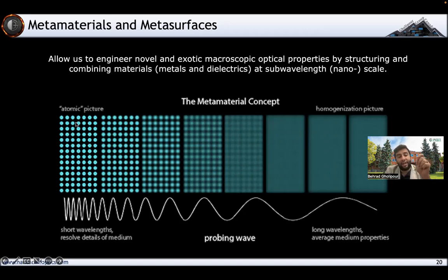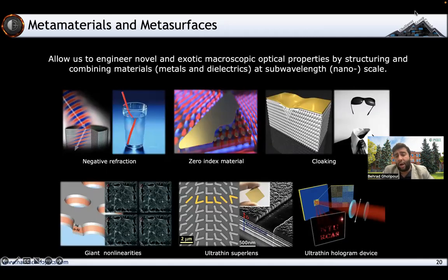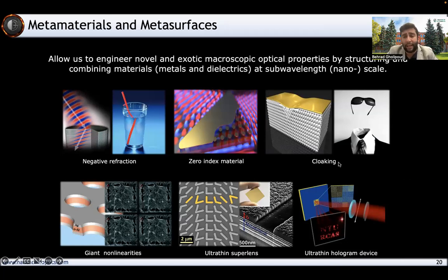But we've very carefully engineered each metamolecule, each of these little nanostructures, nanoresonators, so collectively they all couple together and have a response that the wavelength of operation sees as something that effectively has a particular property, particular index, particular loss, particular transition in refractive index at those particular dispersion at the wavelength of operation. So this particular paradigm has given rise to a large number of different demonstrations over the last 2 decades, a decade and a half, really. People have shown things that are not available in nature readily by just nanostructuring things in a very particular way.